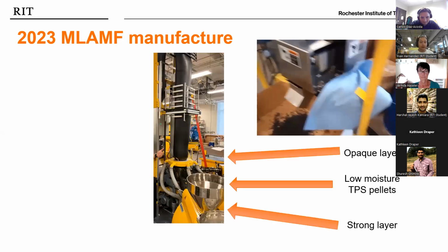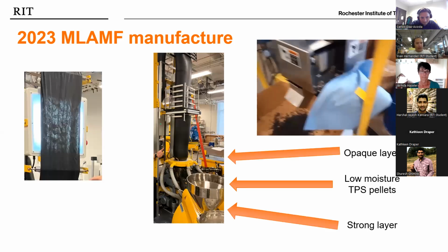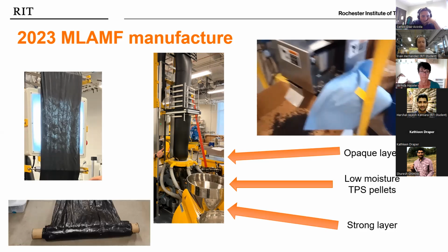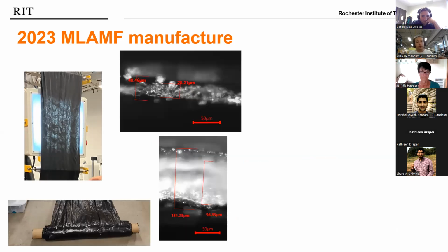So we manufactured it here in our blown film line and looked opaque enough. Of course, it's not as dark as the commercial ones because they use carbon black, but we don't need it actually to be that black. We just need to be black enough to suppress the weed growth. And it was wide enough. So then we went to the field. Well, and yeah, of course, the cross section that are very nice because we can see that thick coarse starch layer in the middle and the sides that are the biodegradable plastics.